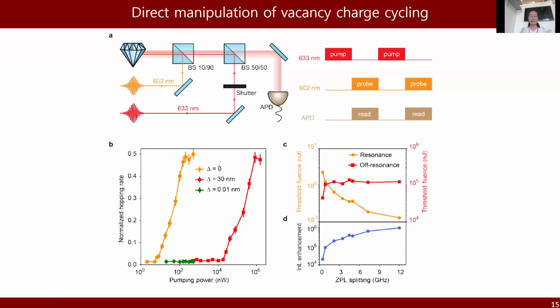Then we can compare this threshold laser power of resonant pump with off-resonant pump. For the off-resonant pump, we use a laser of 633 nanometer. This is a wavelength that is detuned from GeV's resonance frequency so that it cannot directly activate the GeV center. So what this off-resonant laser is doing is that it's directly manipulating the charge cycling of this germanium vacancy. And the laser sequence and the setup is detailed here.